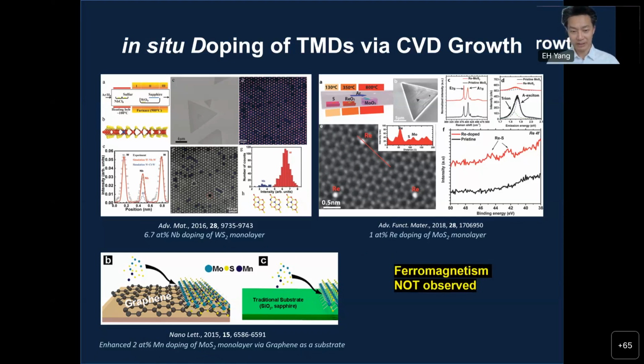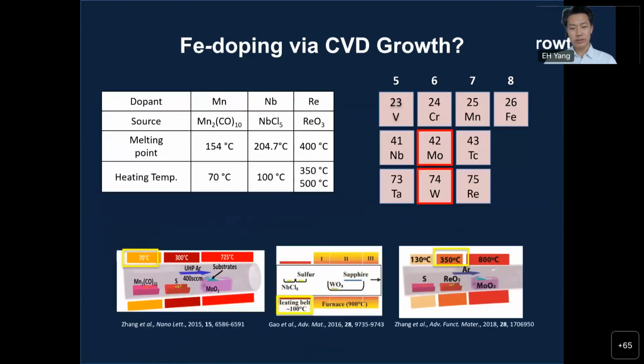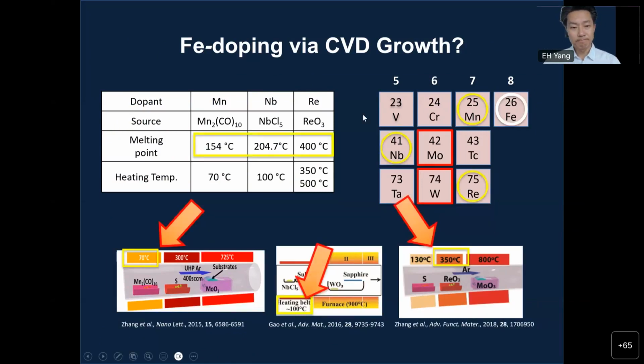So what's missing? My group started looking into doping iron instead of manganese, niobium, and rhenium, because iron is a natural ferromagnetic material, right? The problem here is, unlike manganese, niobium, and rhenium, whose melting points are pretty low, so it's easier to incorporate these into the vapor phase during the synthesis of these 2D materials or these TMDs here.